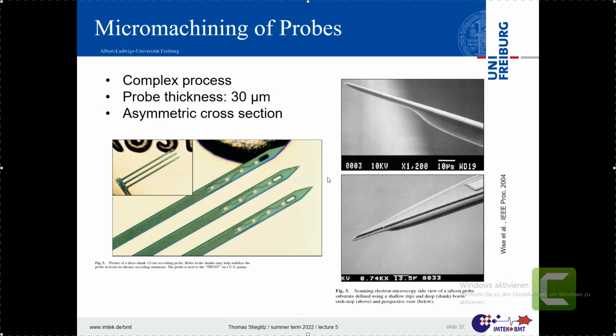Their process, and this is famous, because they thinned the electrodes down from thick 500 micron wafers to 30 microns, which is less than a tenth of that. You see the substrate, this is the back part, an electrode site, and the top layers here in the scanning electron micrograph are insulation materials. The beauty is it's very thin at the beginning, so if you have something that's very thin and very sharp, it penetrates easily, so beautiful. You have that transition, that means it does not create that much damage, it's not like massive posts you have to put in.